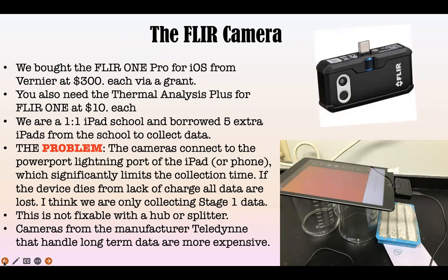I didn't share this with the kids because they had enough to process on their own: the data we were getting was basically stage 1, the cooling of things when the stuff was formed. The kids did take into account the time between mixing. They had to set their cameras up and place the unfilled mold under it and set the whole camera up, then take the mold away, make it, and quickly get it under. So there's probably 1 to 2 minutes between when they had mixed their mortar and when they started recording temperature.